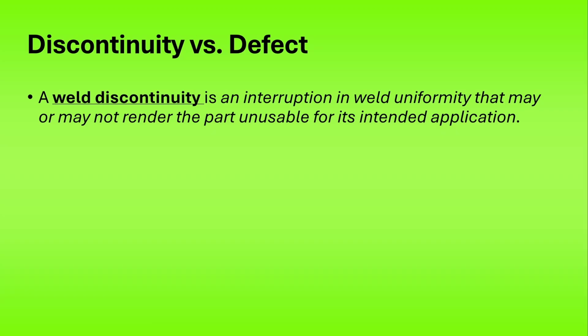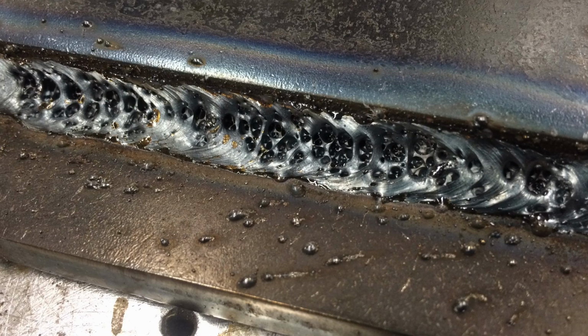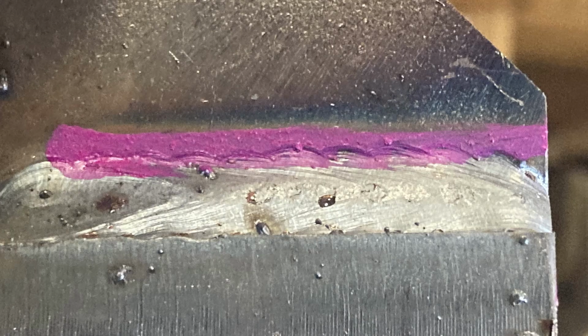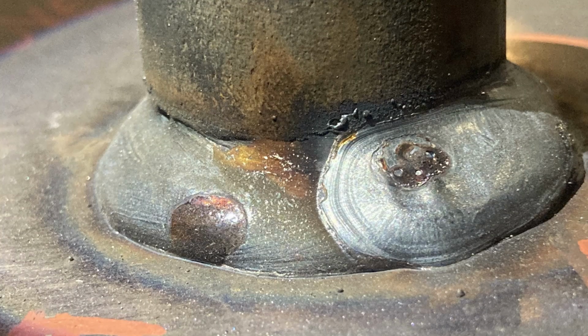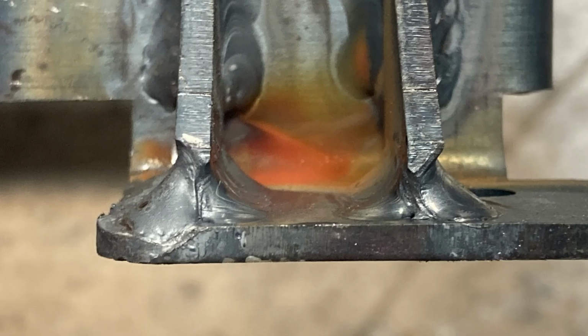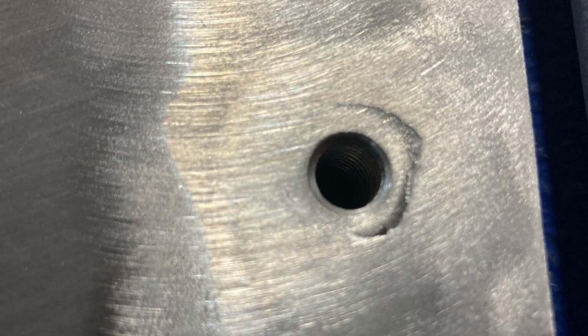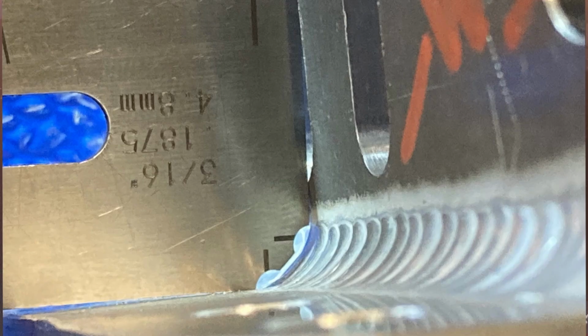Another distinction that's important to make is the difference between a discontinuity and a defect. A weld discontinuity is an interruption in weld uniformity that may or may not render the part unusable for its intended application. Examples of discontinuity begin with and include weld porosity or weld inclusions, undercut, or the reduction and erosion of base material around the weld zone where it wasn't filled in properly, which reduces the cross-sectional area and thereby reduces the strength around the weld. A weld joint could also be underfilled or the weld could be undersized.